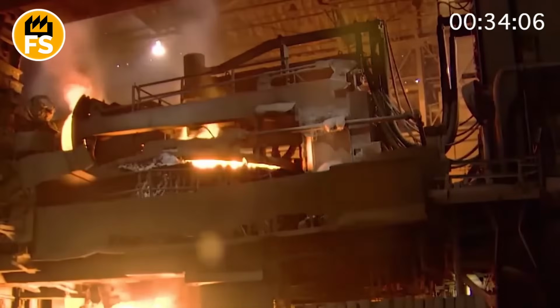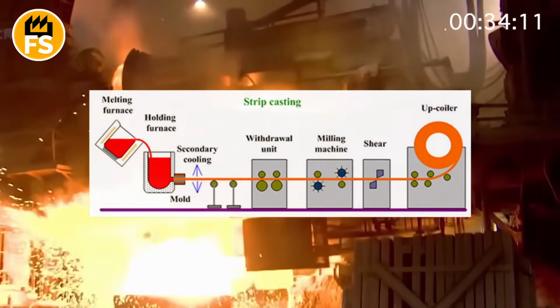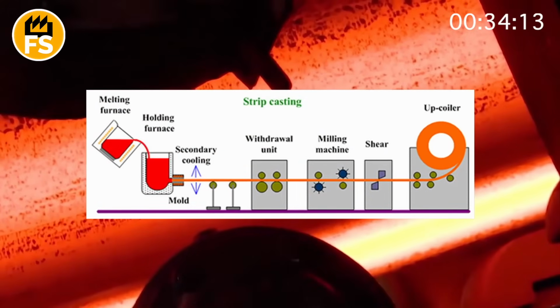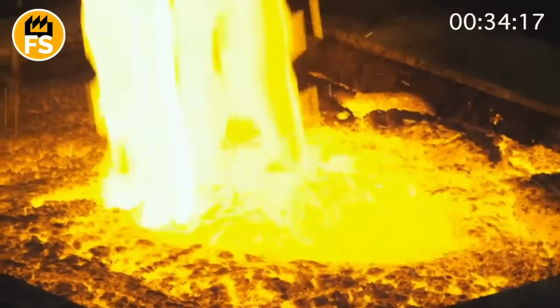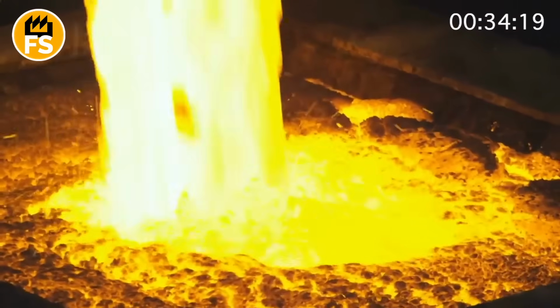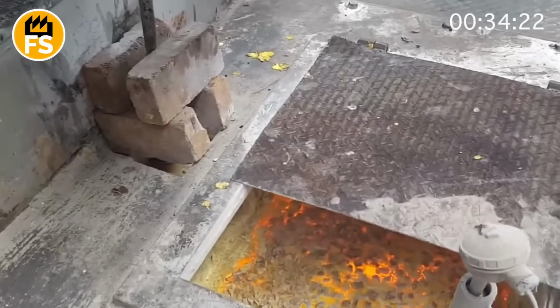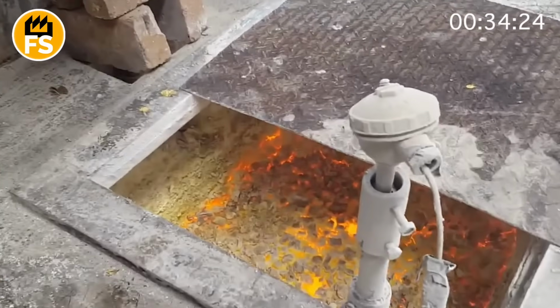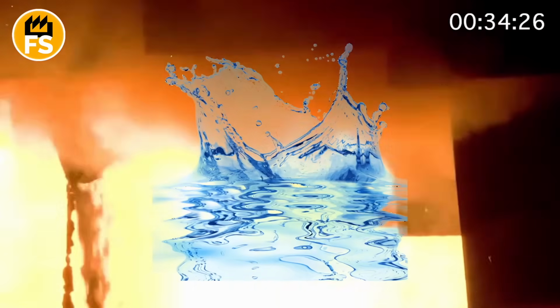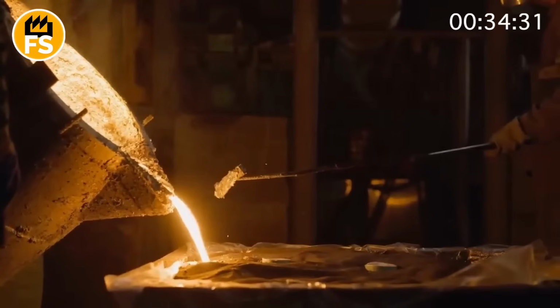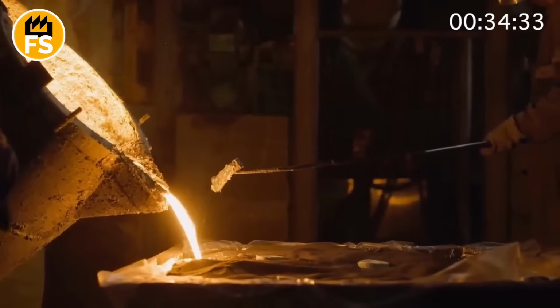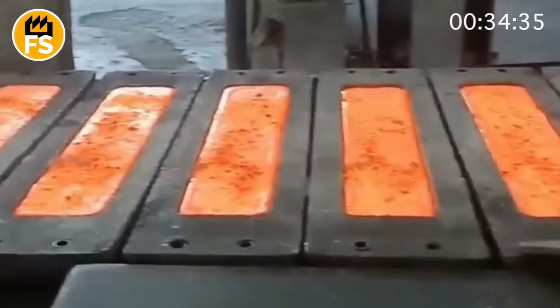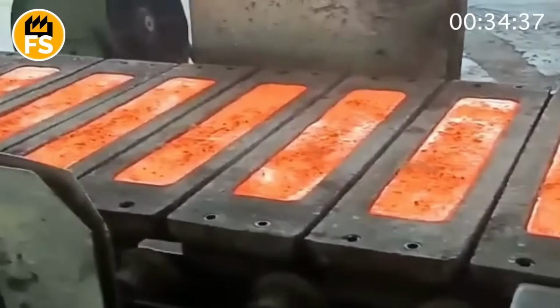After achieving complete melting and homogenization of the alloy, the stage of rapid cooling begins, known as the strip casting method. This is a key moment for forming the optimal microstructure. The molten metal is poured in a thin stream onto a rapidly rotating cooled drum. Contact with the cold surface of the drum leads to extremely rapid cooling of the melt, at a rate of up to millions of degrees per second. Such extremely rapid cooling prevents the formation of large crystalline grains and allows for the formation of an amorphous or microcrystalline structure.